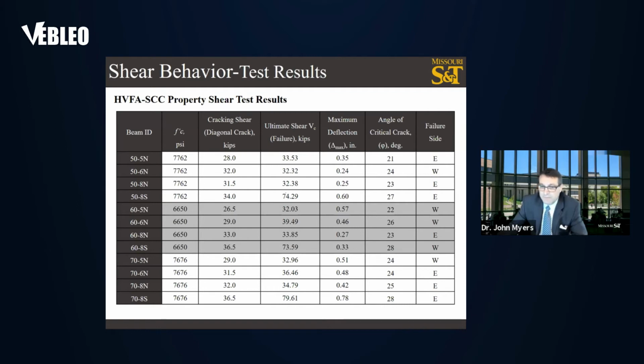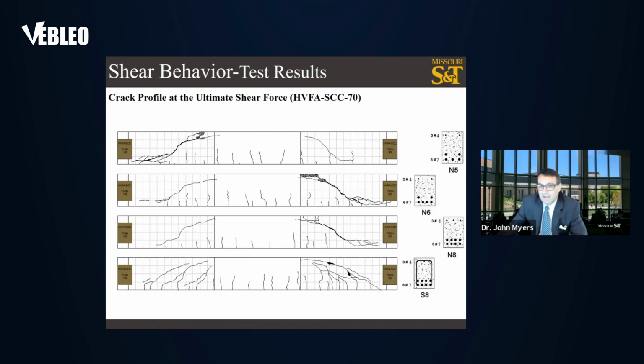Beams with shear reinforcement exhibited high shear resistance, and the shear reinforcement contributions were about 2 times the concrete shear resistance, despite the cement replacement levels being high. In terms of crack propagation, the fine vertical flexural cracks started to propagate at an early stage of loading and appeared around the mid-span of the beams,